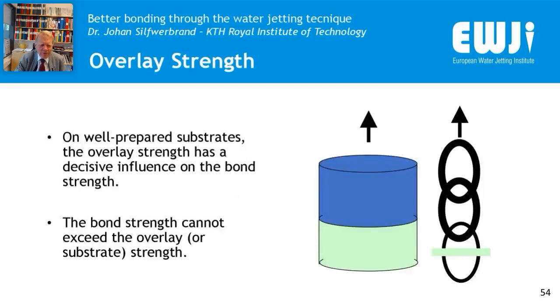And then this is the overlay strength, and here is from reality. Quite often, you cannot remove all old concrete, because then you do not have any bridge to make your overlay on top of. So you need to save some part of the old concrete, and sometimes the quality of that material is not of the top quality, and then when you are testing the bond, you will have a failure inside the old concrete. And so that means that, independent of the quality of the new material, you can never surpass the quality of the material that you leave behind.